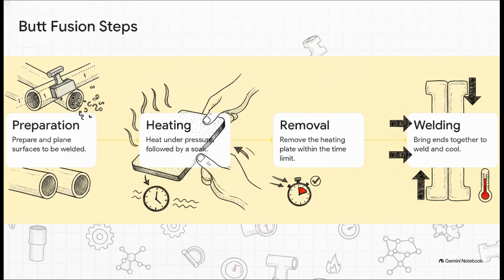Second, we heat the ends against a PTFE-coated plate under a very specific pressure to form that initial bead, and then we follow that with a non-pressurized heat soak to allow for deep thermal penetration. Third, we remove the heating plate, and fourth, we bring the pipe ends together to weld and cool under a designated joining pressure. A successful weld relies entirely on the operator's and your adherence to the pressure and timing profiles defined for these exact steps.